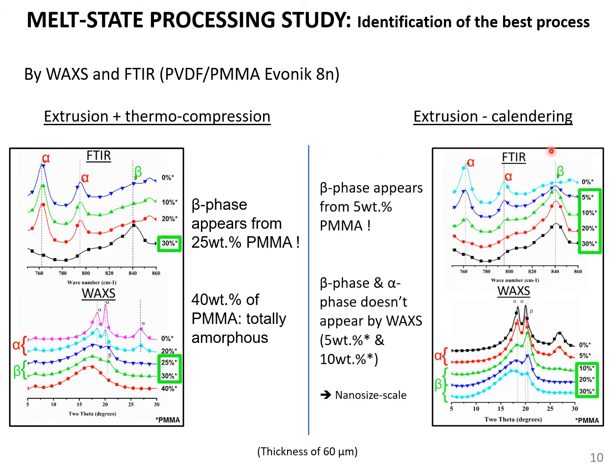Very interesting in the case of the extrusion technique: when you apply a calendering step, you can see that the beta phase appears after only 5% PMMA, and the beta phase is the most important phase at 5% and even at 10%.